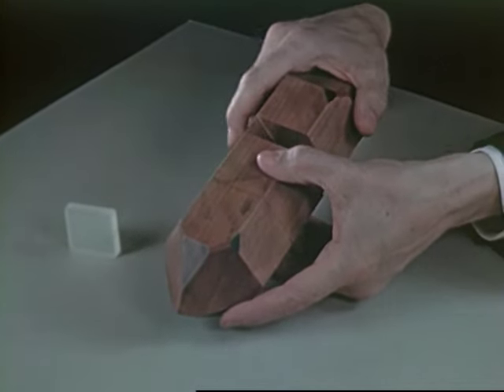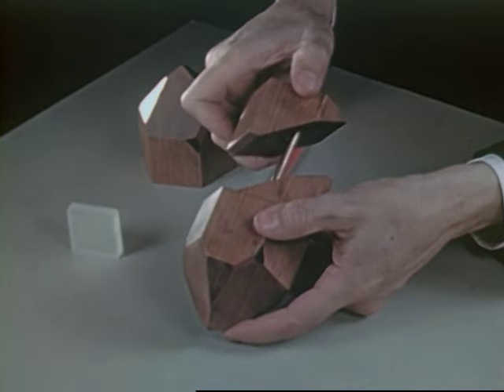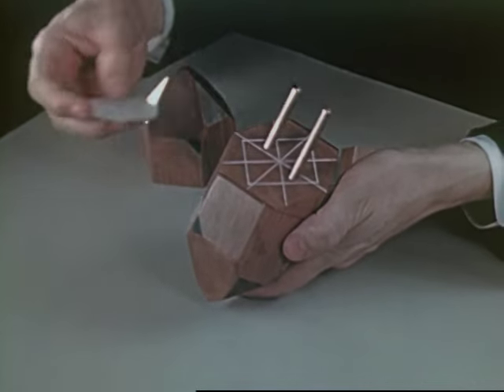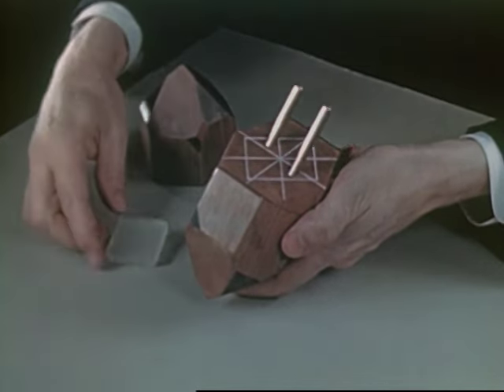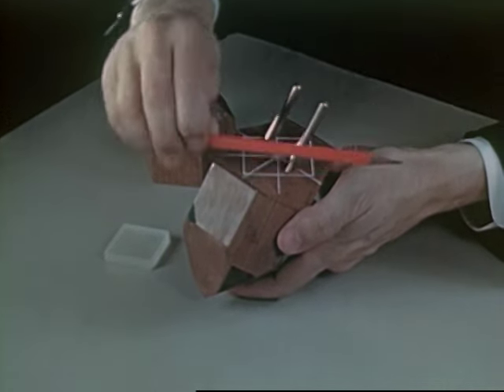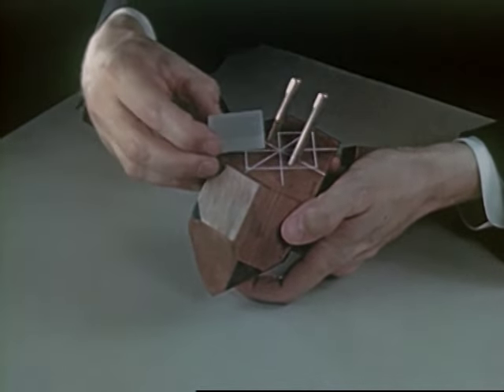We have to saw through the quartz at angles which are exactly right to have the finished plate behave properly in the radio set. The plate whose boundaries are traced in pencil on this wooden model is known as a GT cut plate because of its particular orientation in the mother rock. Holding angles of cut to extremely close tolerances is one of the cardinal principles of good crystal plate manufacture.